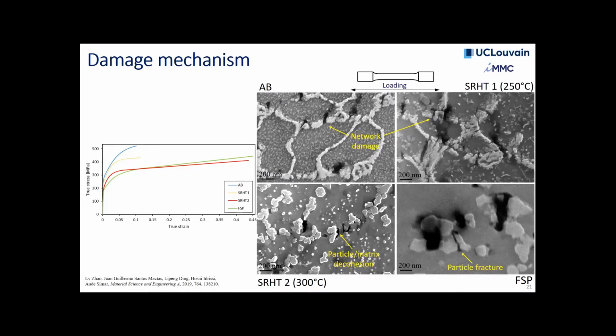So if the goal is to improve ductility, why not try it with a DED approach where you already have the silicon network, which is larger in size. All the features become larger, but you still maintain the silicon precipitates, and you would already have a more ductile material with lower strength, possibly close to FSP. Yeah, that's a good comment. I would tend to agree on that. Indeed, we started with L-PBF, but we could do that on other processes.